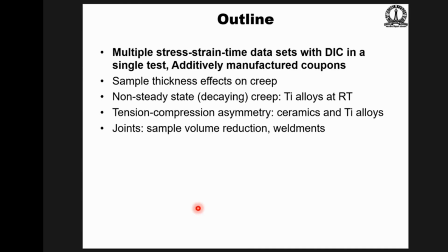Situations where you have tension-compression asymmetry. Bending requires that your output comes both from the tensile and the compressive side, whether you like it or not. So where there is symmetry, the analysis is simple. Where there isn't, if you're flogging this technique, you can say it's a way of getting compression and tension data from the same experiment. But the fact of the matter is it's a problem. If you want tension data, you have to deal with the fact that compression is different. And finally, I'll come to the situation where we have joints, welds, and maybe additively made materials.